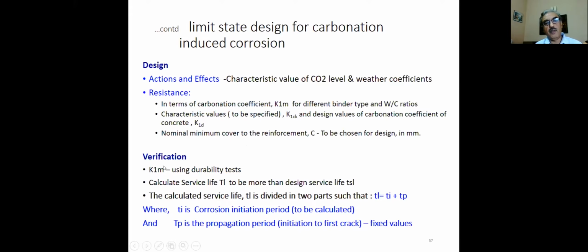So here first of all we have to verify the carbonation coefficient we are assuming. First we assume the water cement ratio, and then we verify through the durability test which we have shown, electrical resistivity or other tests. From that we verify that we are achieving these values. Or through the accelerated carbonation test also we can use.